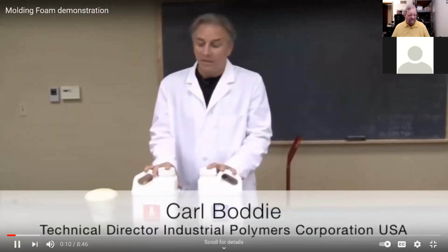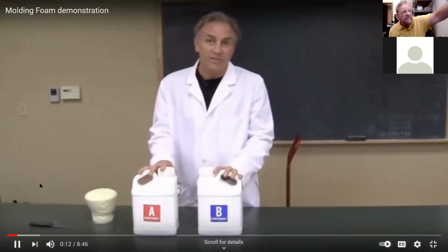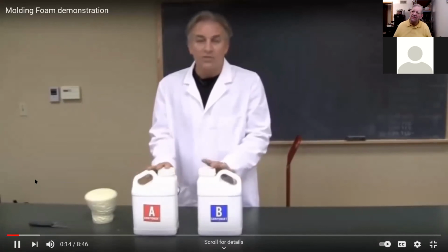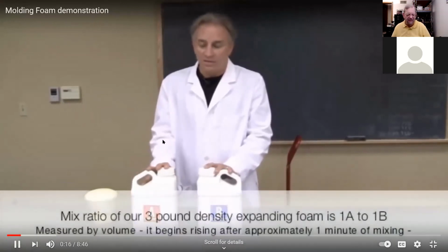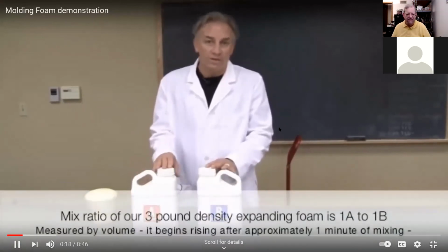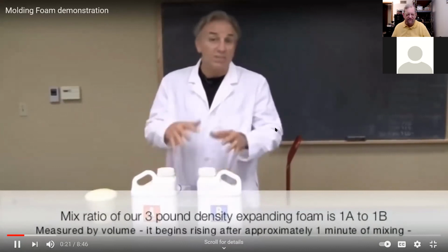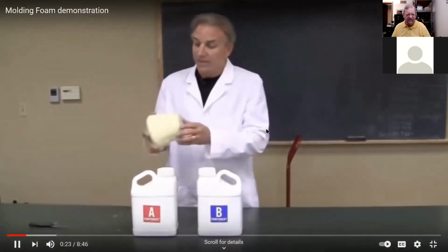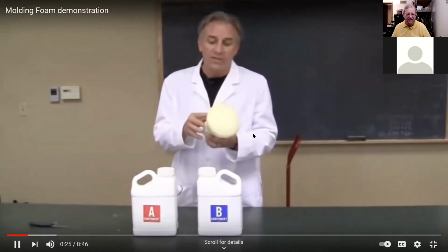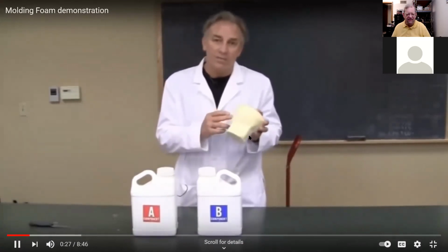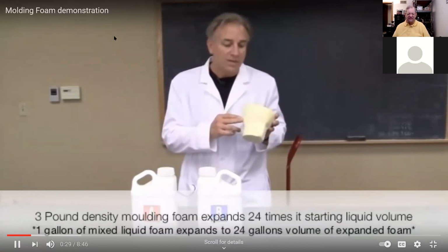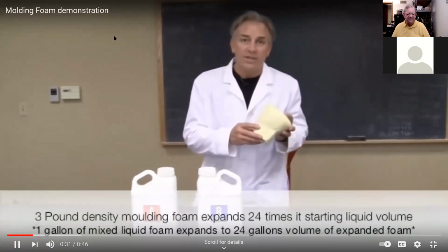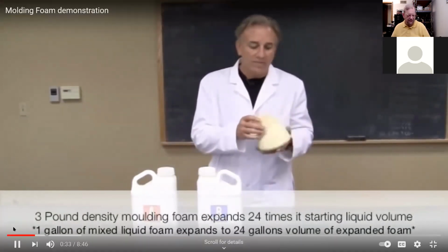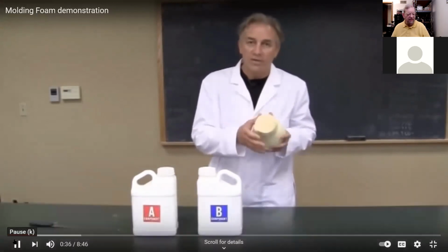Today we're going to talk about molding foam. Specifically today we have a 3 pound per cubic foot molding foam that we want to discuss some of its attributes. This material starts its life off as thin liquids. It's going to be mixed at a 1-to-1 volume measurement, and then it's going to expand to form a very lightweight foam. And as we said, in this case, it's a 3 pound per cubic foot density foam. So it's going to expand 24 times its liquid volume to create a lightweight, non-absorbing,